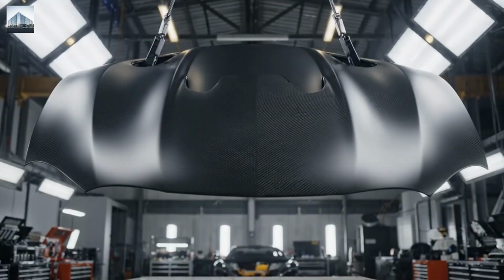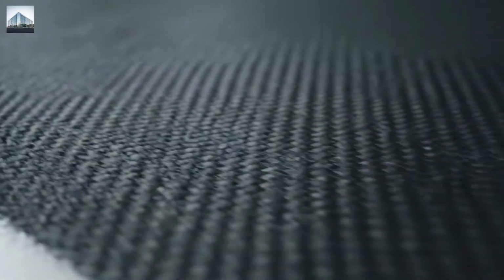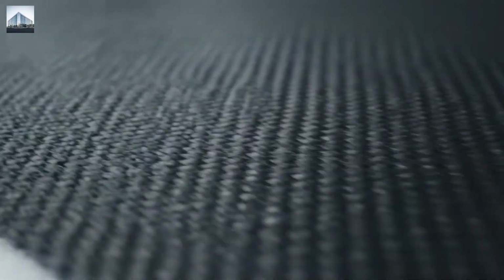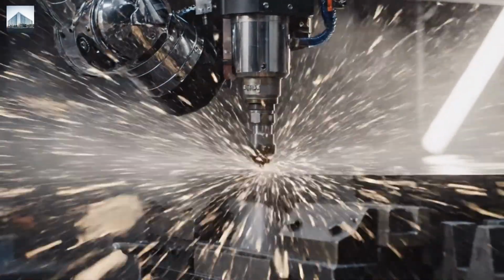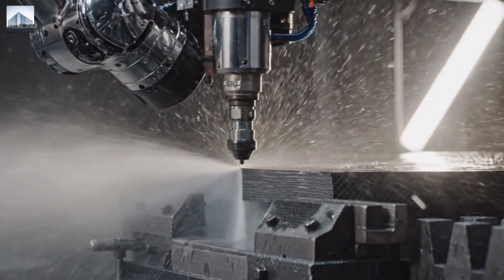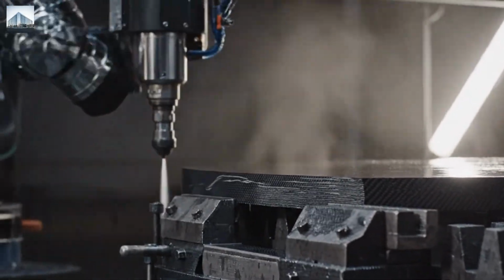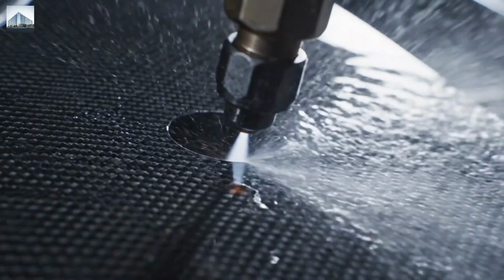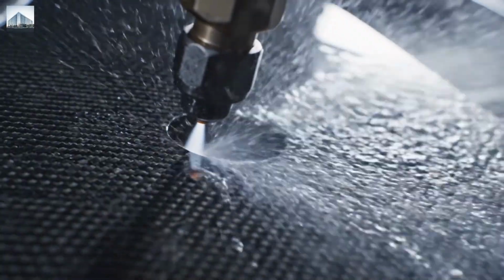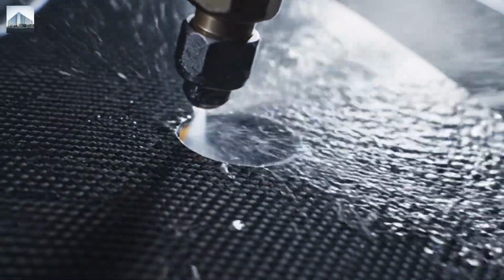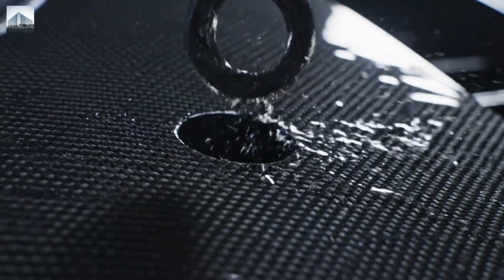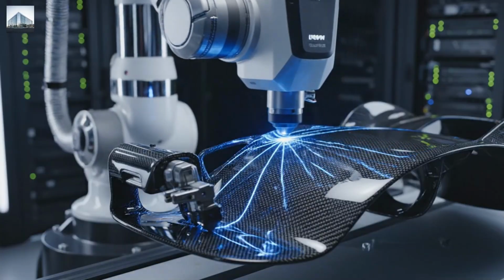They will spend the next several hours in this high-pressure environment, undergoing a chemical transformation that turns fabric into stone. The door seals shut with a heavy mechanical thud. Once locked, the environment inside will be completely isolated from the outside world for the curing cycle. On the control panel, engineers set the cure cycle. The temperature will rise to 150 degrees Celsius, while the internal pressure soars to 6 bars.